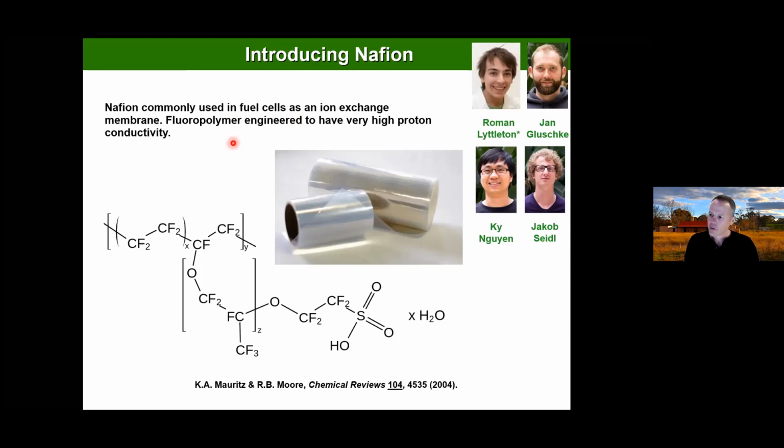It's a popular material in that application because it has a very high protonic conductivity without needing to load it up with salt. Essentially, the way I like to colloquially think of it is that it's Teflon with sulfonate groups attached, so that it forms this nice structure with water pores through it, where ions can migrate at very high speed through those pores inside that material.